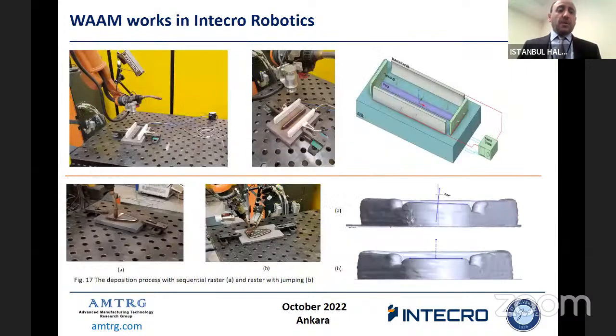And we also have a lot of work on WAAM systems. One of them is that we try to keep the heat around the production area, so we have some shielding systems, and we did a lot of experiments. We also developed some tool paths or deposition paths, so as not to accumulate the heat in a very narrow area. Therefore, we changed the tool paths. We did experiments and trials, and we saw that when we change the deposition paths based on the temperature accumulation, we get good results on the geometry. But we are still doing the experiments, we continue them.